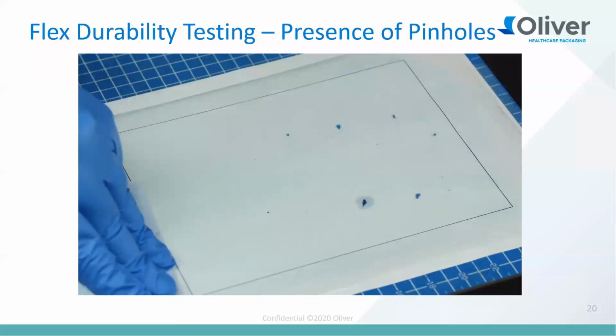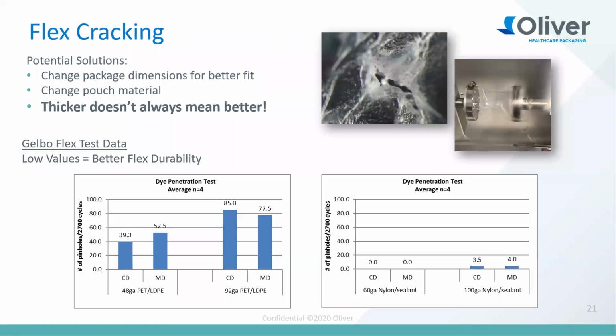So on the next slide, we have the results of this test. As you can see on the bottom of this slide on the left-hand side, you can see the high amount of pinholes that are present in this 92 gauge polyester. This area, 85, 77 pinholes, that's an average of about 80 pinholes on that test. And you can picture that 8.5 by 11 inch, our standard piece of paper for printing, has about 80 pinholes. That's quite a bit. And if you look on the left of that in the same graph, that 48 gauge is a little bit thinner gauge polyester, but it has about half as much. So the message here is really thicker isn't always better.